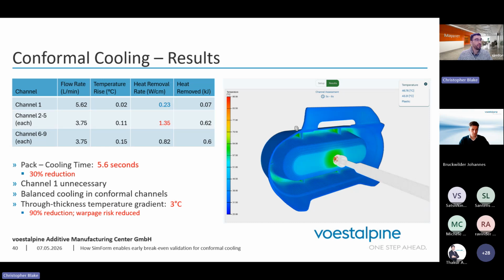Here are the results. So we've reduced the pack cooling time to 5.6 seconds. That's what's predicted by the simulation. So that's a 30% reduction. So we're confirming that there's a good time savings there. Again, we've confirmed that channel 1 in the stripper plate is not removing much heat, so this is likely an unnecessary cooling channel, or one we could start to think about whether we need it. However, in comparison to the conventional cooling, we are seeing much more balanced cooling in the conformal cooling channels. And most importantly, we're seeing an important reduction in the temperature gradient through the wall thickness, going down to 3 degrees. So quite a significant reduction there, which is going to reduce our warpage risk.